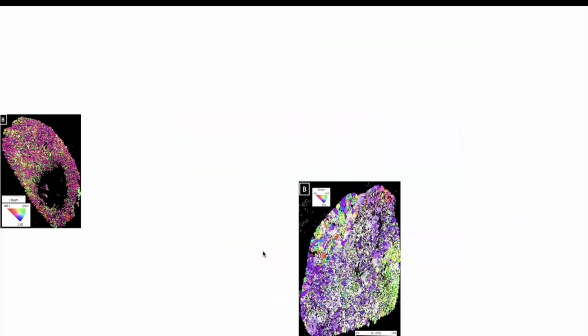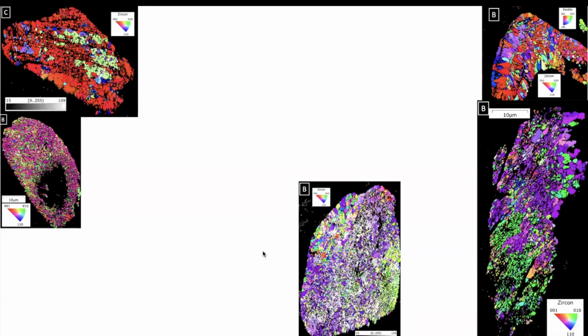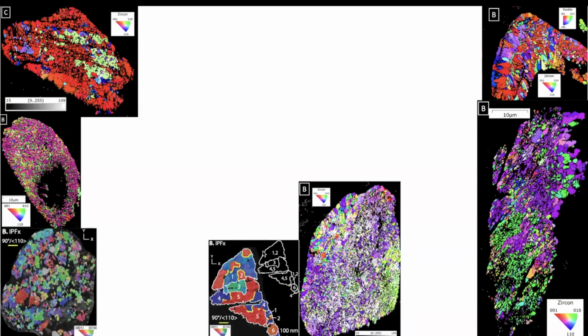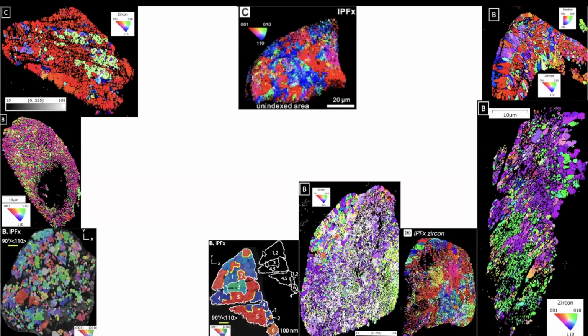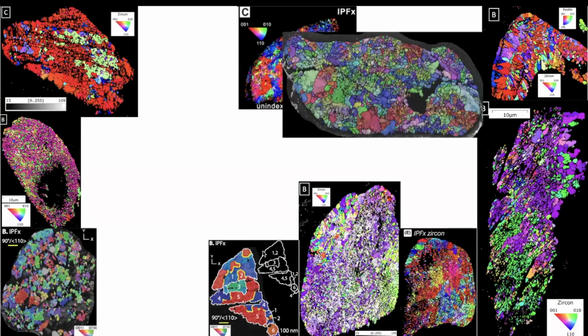So if we start looking at more, these are the ones that I talked about today, but here are a couple of the other ones that I have done maps of. You can start to see that there are huge textural differences within this category. So this could be like a polyphyletic grouping, if you think about it in biology terms. Some of these grains have huge domains of a single orientation. Some of these grains have zirconia or silica embedded within granules of zircon. Some of them have remnant Reidite, some of them don't. Some of them have planar fabric, some of them don't, right?